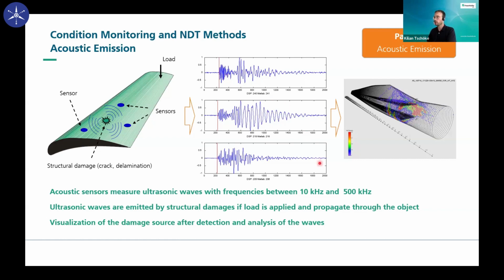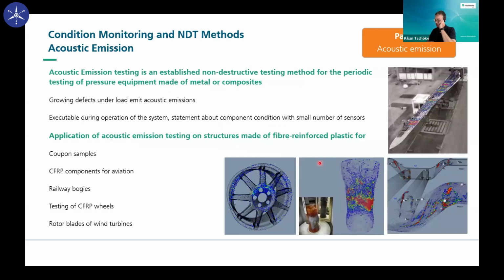We use this technique, the so-called acoustic emission technique, for monitoring a lot of different applications and examples. You can, for example, investigate or monitor the growing of defects. For example, if a delamination increases from time to time, it can be done in operation of your systems. There's no need to stop your system until you will get information that, okay, there's a critical damage.